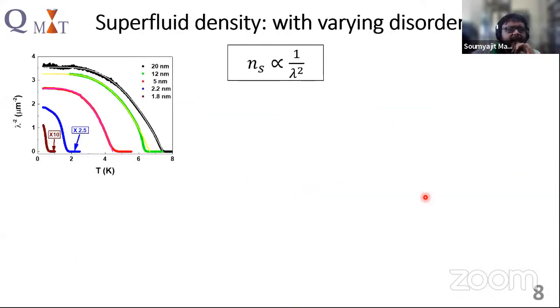So let us see what result we have got. Here is 1 by lambda squared, the temperature variation of 1 by lambda squared for different thicknesses. The black curve is the highest thickness, the 20 nanometer, and all the other curves are in decreasing order.